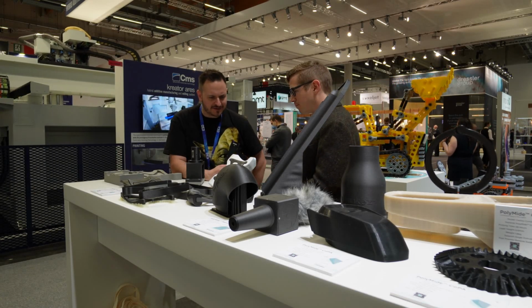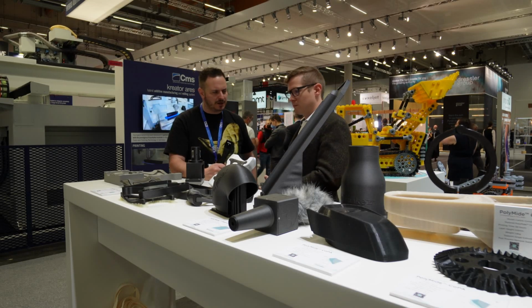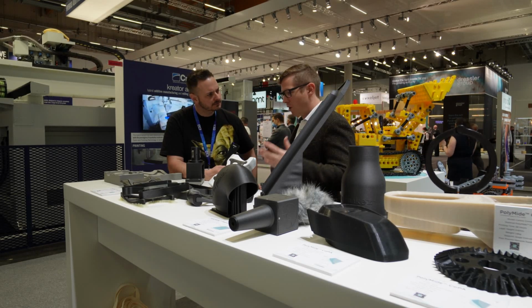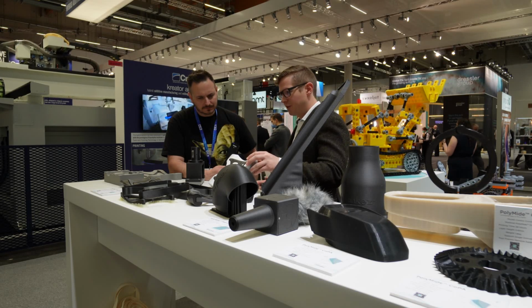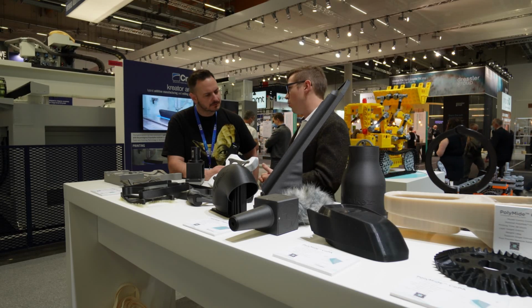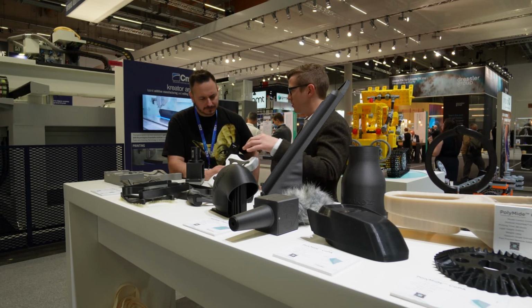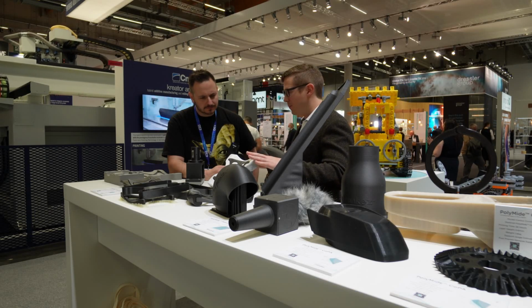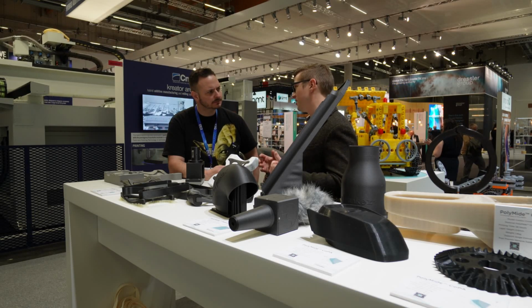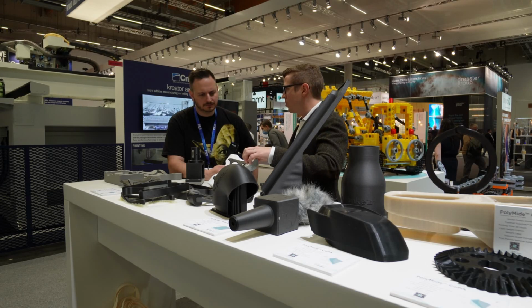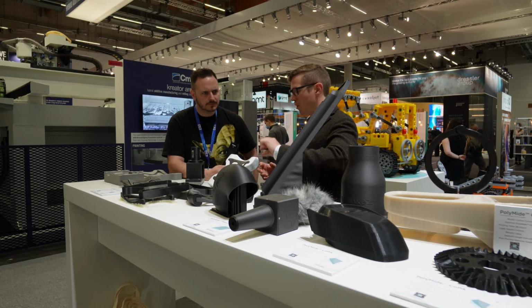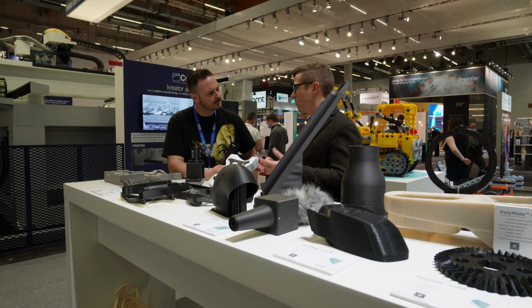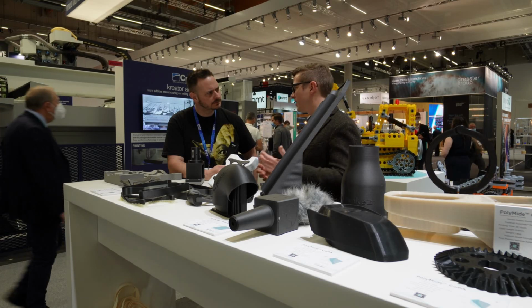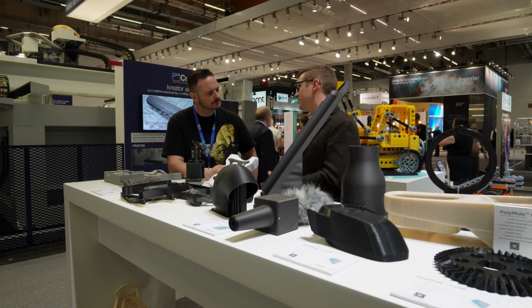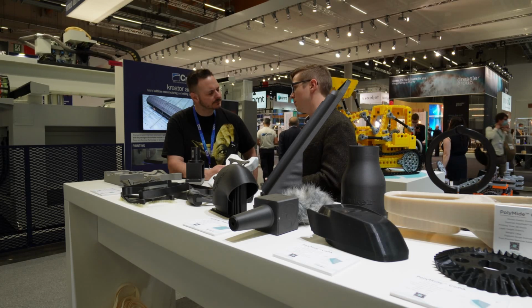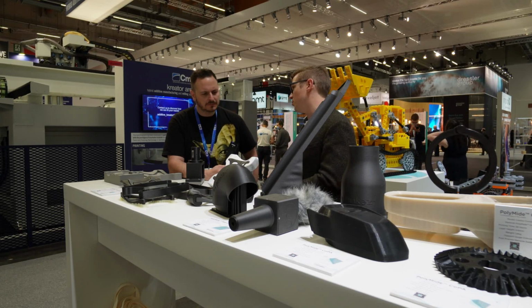So in regards to the strength there, what kind of applications do you think people are going to be using this type of stuff for? So one application we have here is a steering wheel mold and a steering wheel inner core. So you print the mold in PA12 because you want a nice surface finish, and then you print the inner core in PA6CF, and then you wrap one layer of carbon fiber around the core, vacuum the whole thing, and you can bake it in the oven. Most resins cure at about 120. Right. The heat resistance is good up to 200.